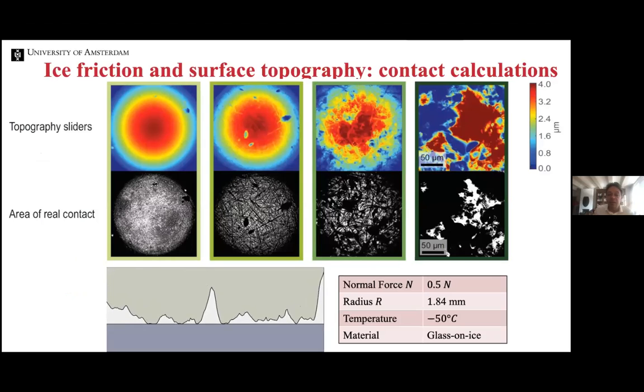The non-Arrhenius behavior is perhaps even more interesting. So what we do is we take the roughness of the different sliders and then do a contact calculation using a finite element package that is readily available. From such a package, you get the area of real contact between your sphere and the ice, supposing that the ice is actually smooth. And if you know the normal force and you know the contact area, you know the contact pressure.